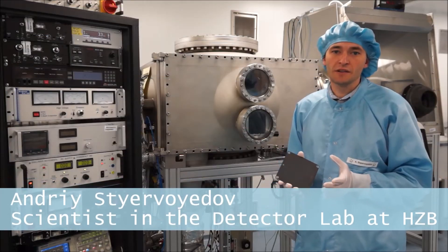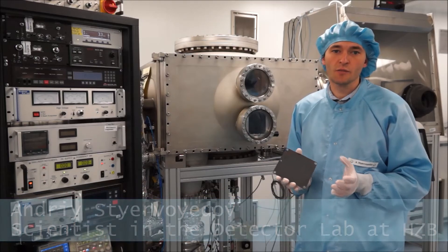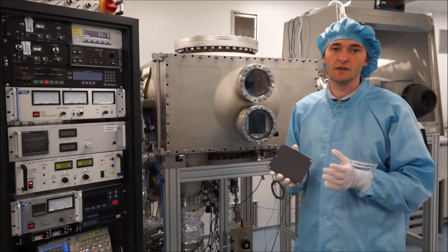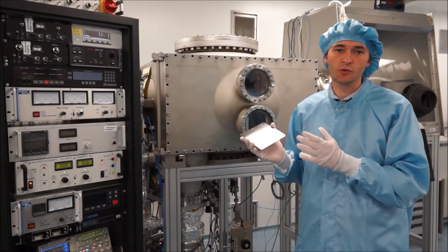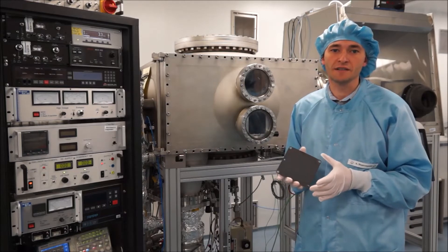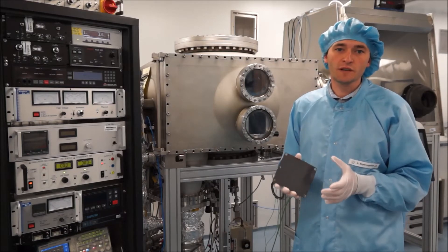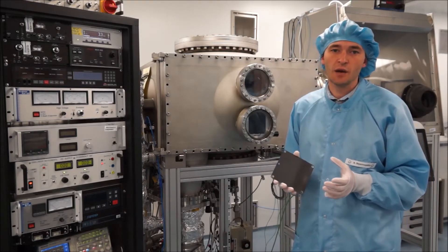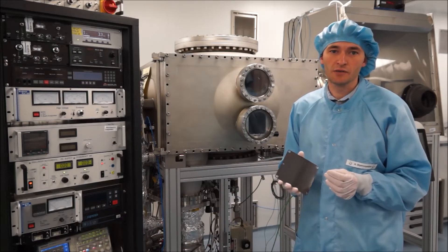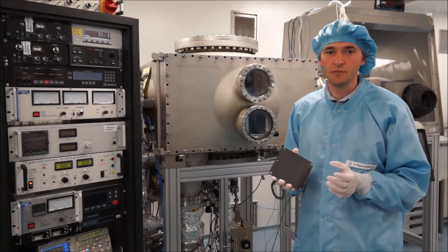At the moment, magnetron sputtering is a standard method to produce boron and boron-carbide layers, and we are using this technique to create high quality layers as reference. To improve the adhesion and quality of such layers, we apply high-power impulse magnetron sputtering, so-called HIPIMS.